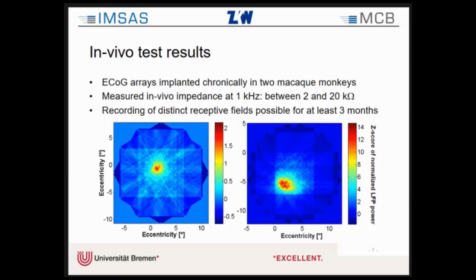And with this experiment, we are able then to map the visual field of the eye to the position of the activity on the visual cortex. And this is shown here in the 2 figures. The results you see here are for 2 different electrodes recorded 3 months after implantation. And you see here the X and Y eccentricity of the visual field, and the color bar gives the normalized LFP power during the recording. And so the results show that we are able to distinguish between different electrodes.